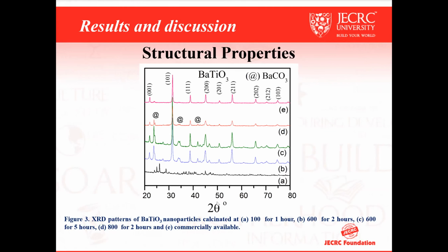So if we see here, this A is barium titanate synthesized with the help of the sol-gel method, which is dried at 100 degrees centigrade, and the peaks recognized as the formation of barium titanate are improper, and that is what the amorphous nature is showing here. But as the calcination temperature rises,